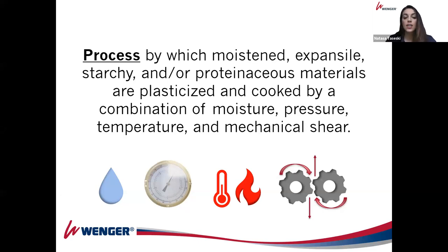Can you predict what's going to happen in the extrusion process? To an extent, because you're limited by your understanding of the diversity of that natural material that you're going to be working with in foodstuff. Whereas in plastic and polymer extrusion, you can more or less have conditions that are predictable, or materials that have certain predictable or reversible behavior in the extrusion process. And after the extrusion process, with foodstuff, that is not the case. So with extrusion, we're relying on moisture, pressure, temperature, and mechanical shear.